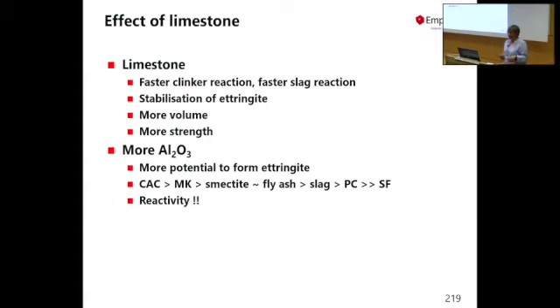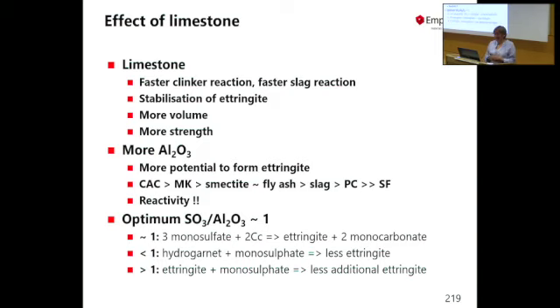Okay, but this was mostly on Portland cement. I just wanted to summarize a bit the effect of limestone. I didn't show all the things I would have about it because we don't have so much time, and I want to speak about blended systems and other systems. But if we add limestone to Portland cement, we have a faster clinker reaction. We stabilize the ettringite. We have more volume. We have more strength. It's cheap. I haven't even written that there. We can boost the effect by adding other SCMs like metakaolin, like fly ash, and similar things. The effect itself depends a bit on the sulfate to aluminium ratio, because this is the thing that determines how much ettringite you will form.